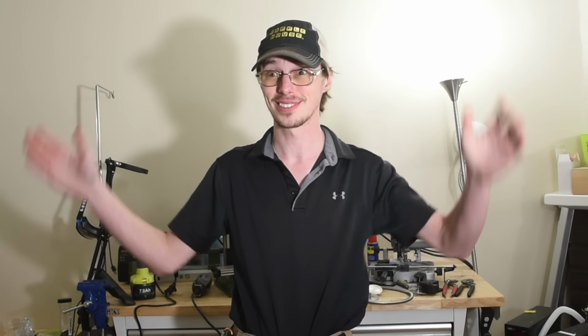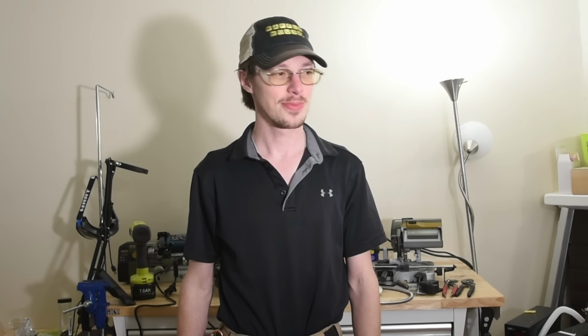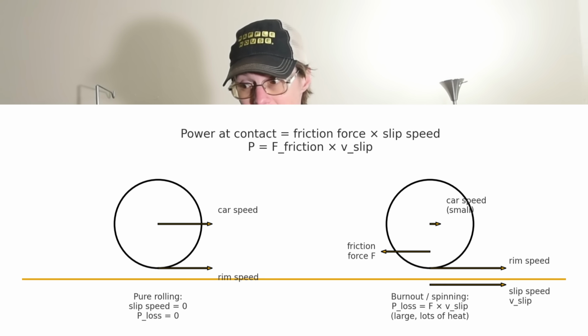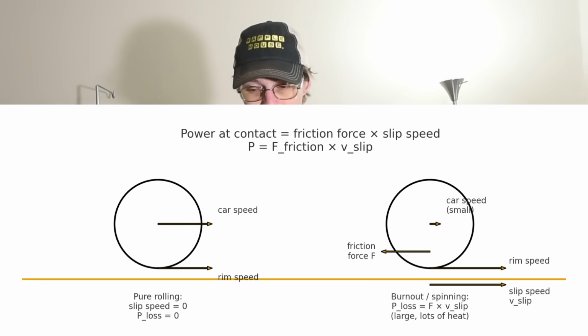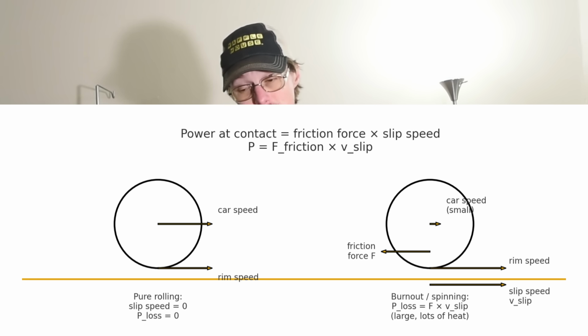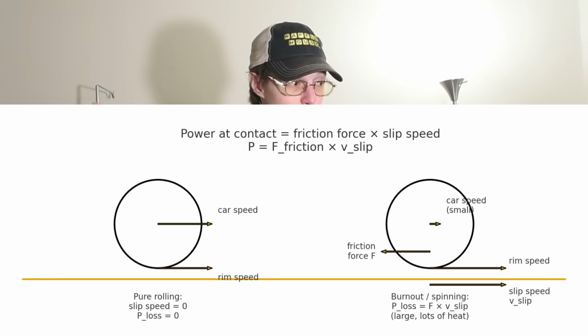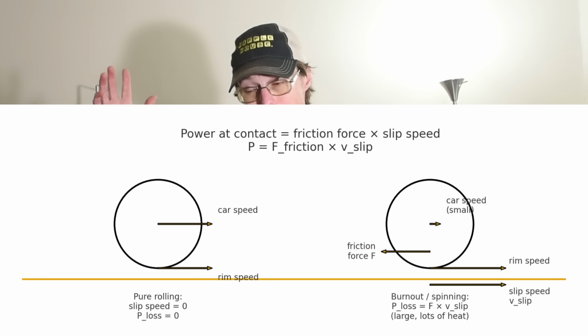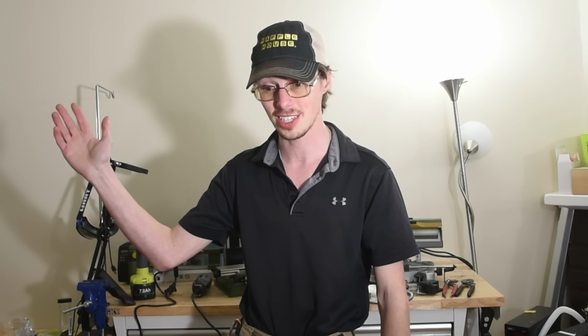They just work. It's like magic. Or really, I guess that's the magic of power. P is equal to F times V, force times velocity. The power dissipated by the wheel is how much force of friction is applied to the surface times how fast the wheel is spinning. If you can keep the wheel spinning fast enough, and you have enough torque to overcome the force of friction, you can make the metal flow any way you want.